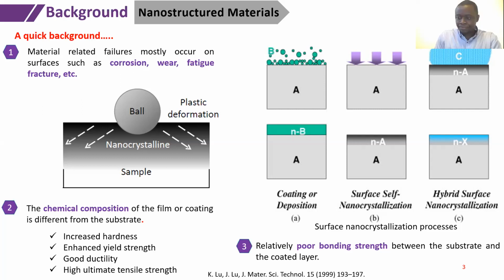Because of this problem, there are processes that have been developed. As you can see, we have three of them: the coating or deposition, and the hybrid nano-crystallization. However, the major problem associated with the coating and the last method is that the chemical composition of the substrate and the material is somehow different, and this may lead to problems. Most importantly, there's relatively poor bonding between the surface layer and the substrate, and this also leads to very poor corrosion resistance. Hence, we come up with a method, as you can see with my cursor. This method creates nano grain layers on the surface layer through plastic deformation. The most important thing about this method is that it improves the mechanical properties of the material: hardness, yield strength, ductility, and tensile strength.